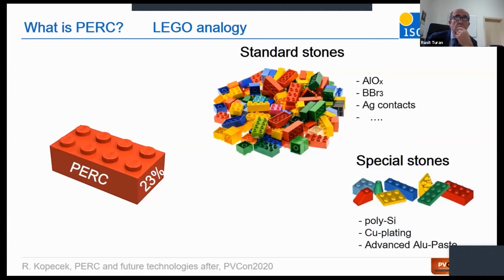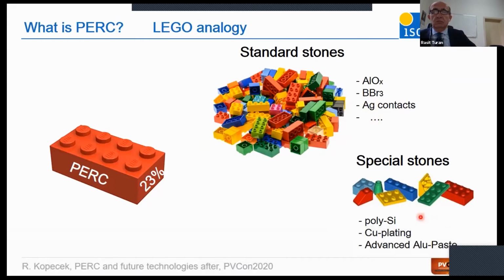The question now is which stones to use to make it more powerful, like TOPCon-like. Then of course aluminum oxide is already a standard stone, as is boron diffusion using silver contacts. But in order to make it really more powerful and low cost, the special stones are still not matching. So for example, the polysilicon depositions, we still have to find a solution here, or because of the full silver metallization, for example, we have to switch to advanced aluminum paste or look into copper plating again.